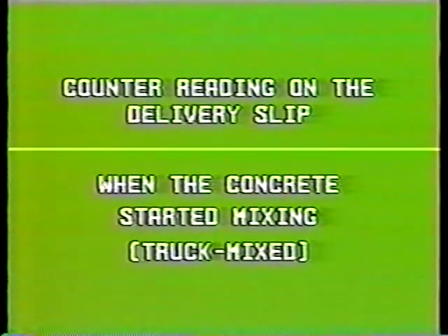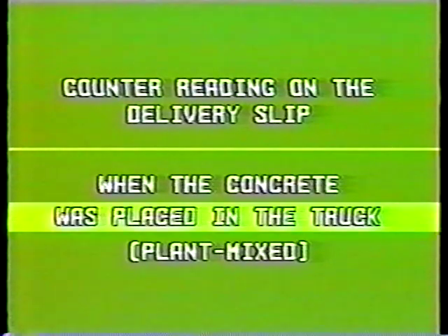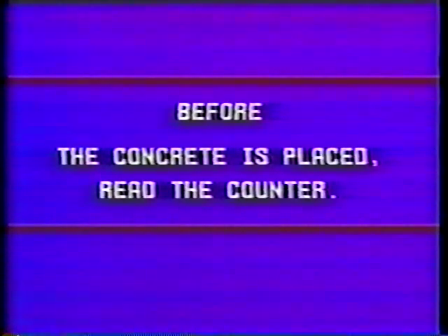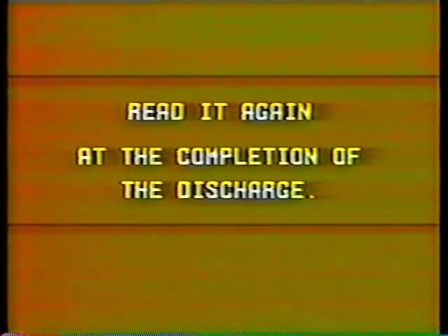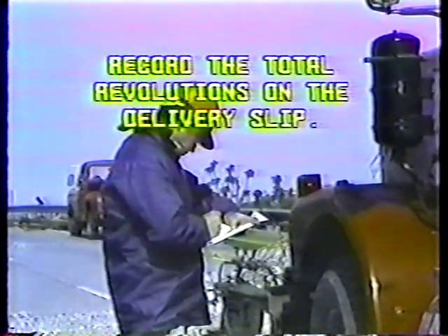The time is critical. Concrete must be placed within 90 minutes after mixing. So if the concrete was batched at 2 o'clock, it must be placed by 3:30. The revolution counter on the truck records each revolution of the drum, at both mixing and agitating speeds. The concrete will start to segregate if it's mixed too much, so it's important to keep an eye on the counter. The counter reading on the delivery slip was taken when the concrete started mixing, if it was truck-mixed, or when the concrete was placed in the truck, if it was plant-mixed. Before the concrete is placed, read the counter, and read it again at the completion of the discharge. Then record the total revolutions on the delivery slip.